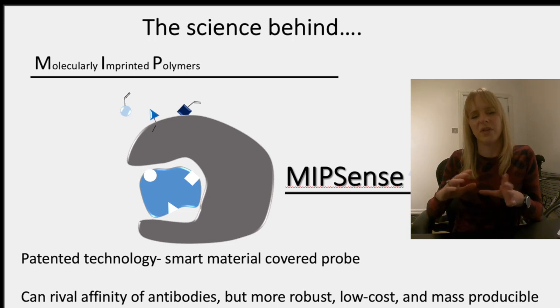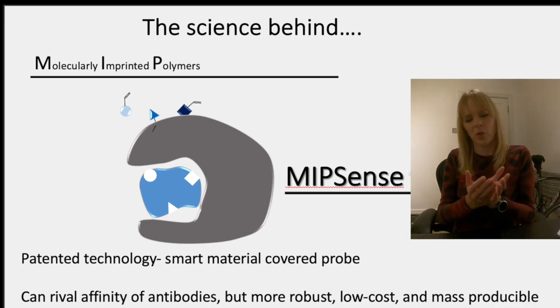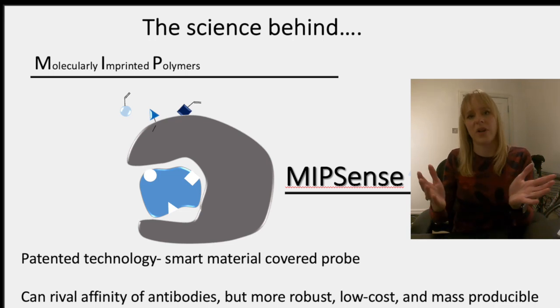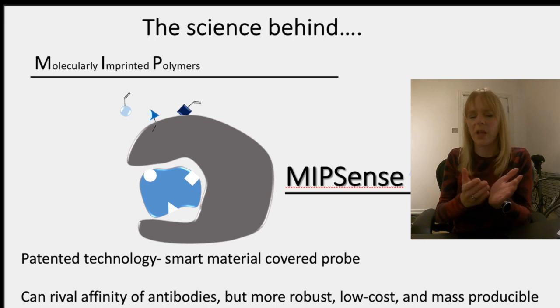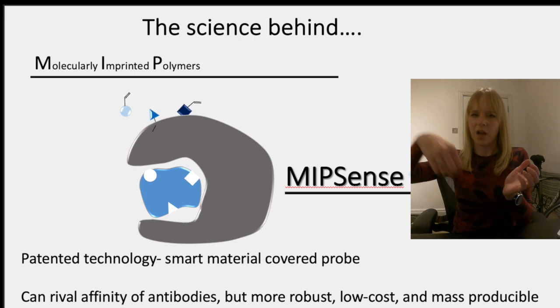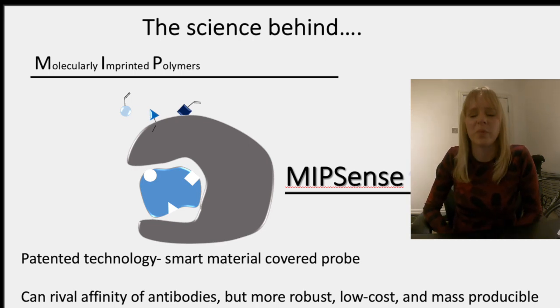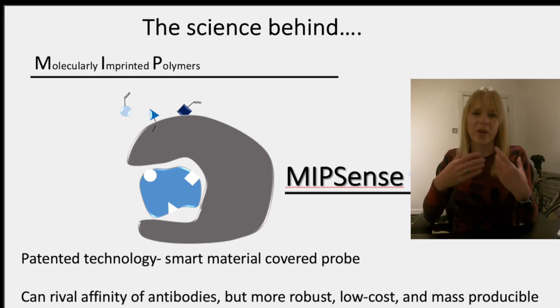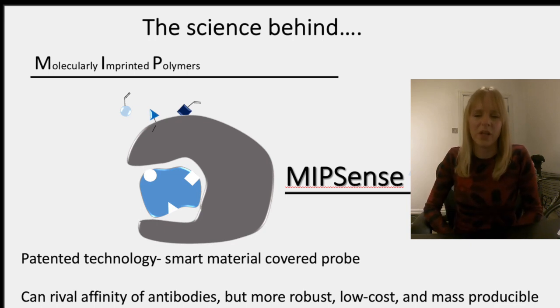And here you can briefly see how this works. So we cover our probe or our electrode with this MIP material, and this is done by having a templated polymerization, and after you remove the template you end up with binding sites that resemble the size and the shape of what you want to detect, but there's also a chemical interaction between them. So essentially you get a highly porous material with high affinity binding sites.